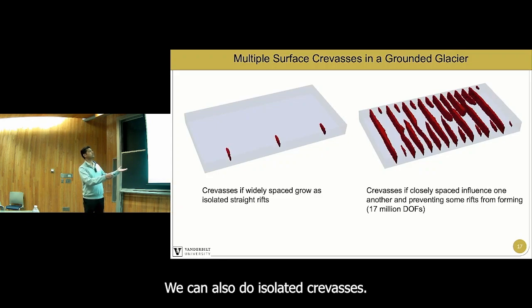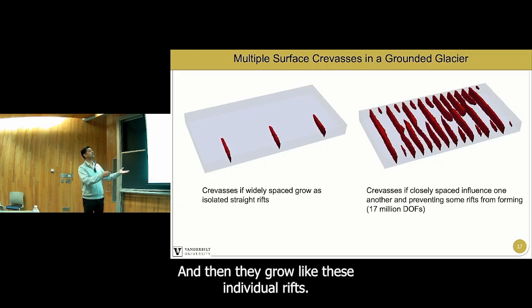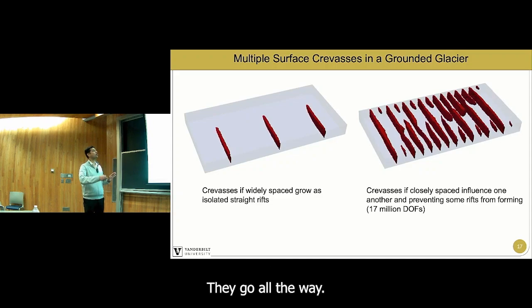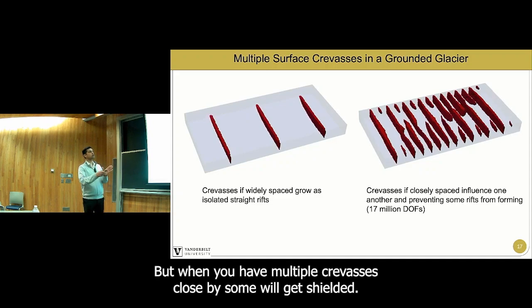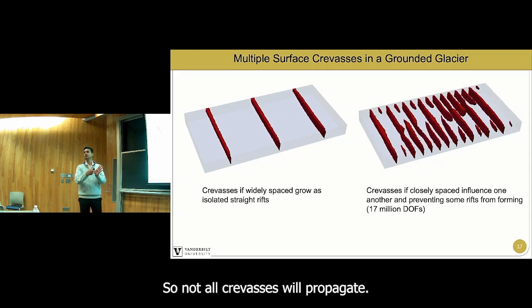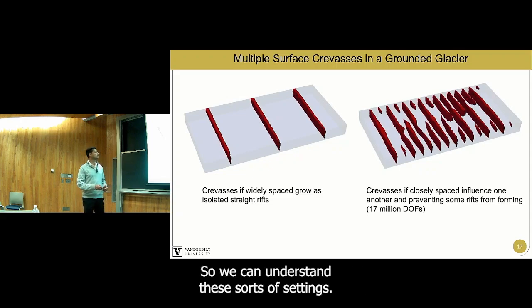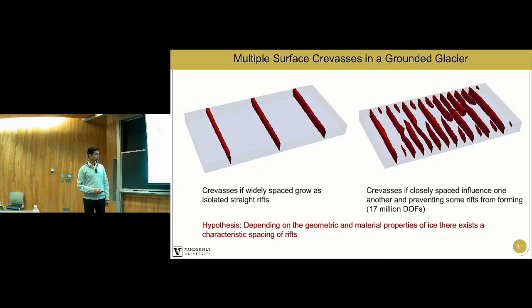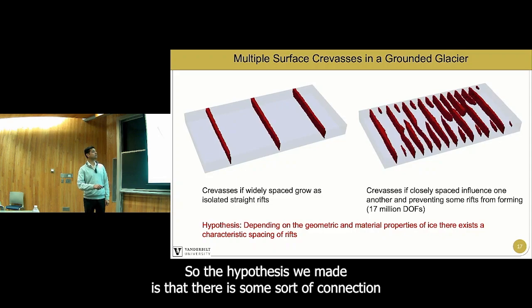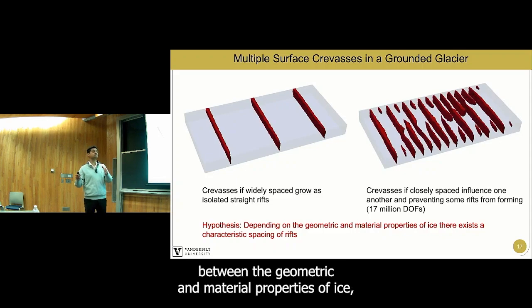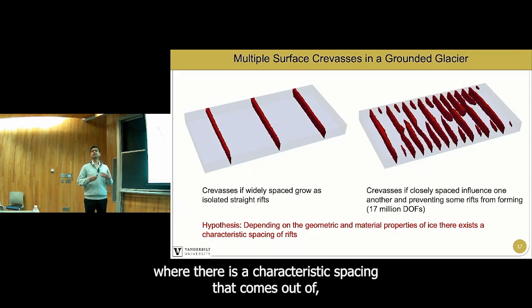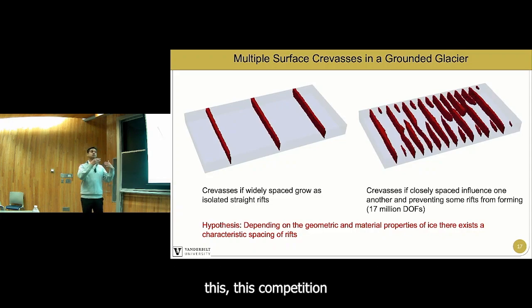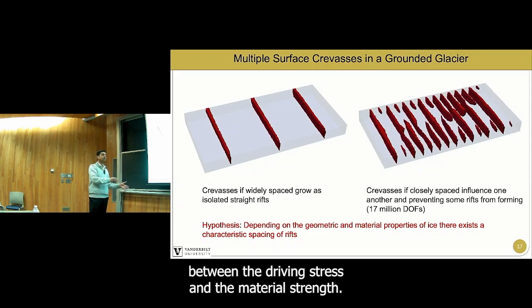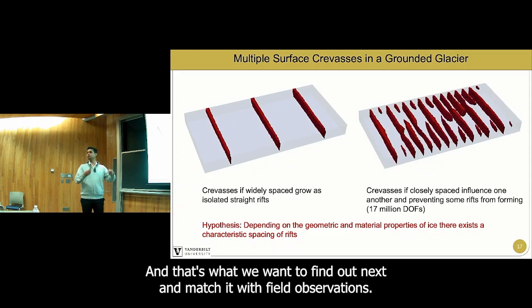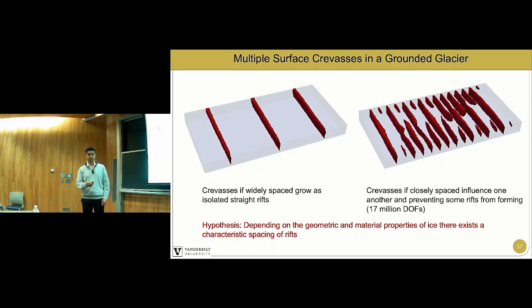We can also do isolated crevasses, and then they grow like these individual rifts. They go all the way. But when you have multiple crevasses close by, some will get shielded, right? So not all crevasses will propagate. So we can understand these sorts of settings, and we can make hypotheses, right? The hypothesis we made is that there is some sort of connection between the geometric and material properties of ice, where there is a characteristic spacing that comes out of this competition between the driving stress and the material strength. And that's what we want to find out next and match it with field observations.